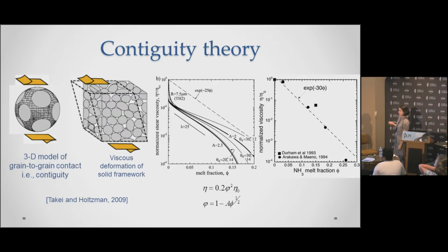And I don't know if that's because this one point that I cherry-picked doesn't really capture something going on at the low melt fraction, or if this process, which is specifically designed for the math that they did, is for diffusion creep, and these are probably deforming primarily in dislocation creep, if that affects the response. But at least for the magnitude of the viscosity drop, models like this can be really powerful.